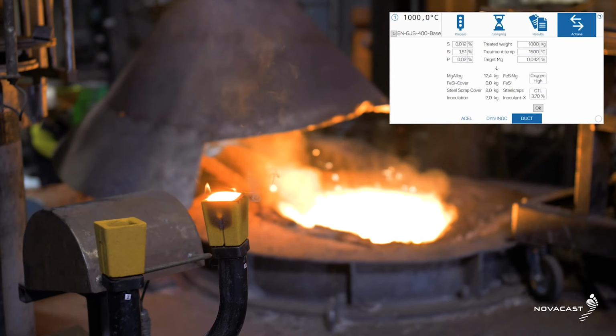Treated weight and temperature are adjusted, depending on the temperature reading and also on the accurate treatment weight in the ladle. We have to know that ATAS is calculating, based on the oxygen calculation from the melt, exactly the amount of magnesium to add.